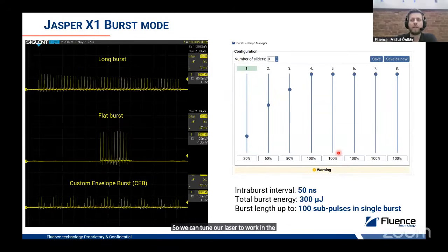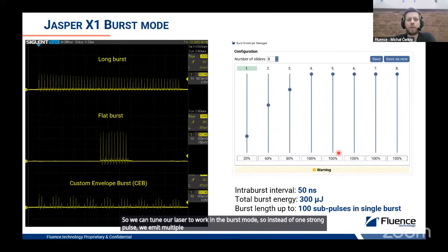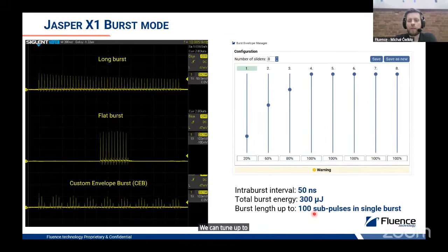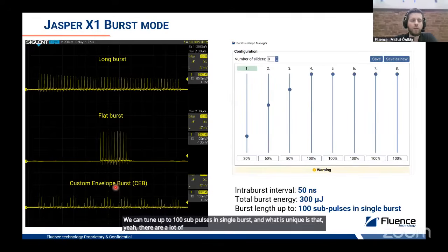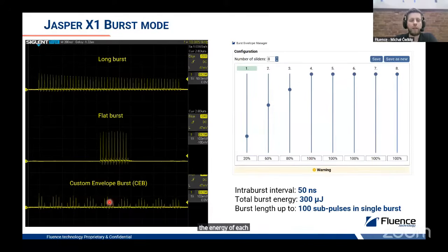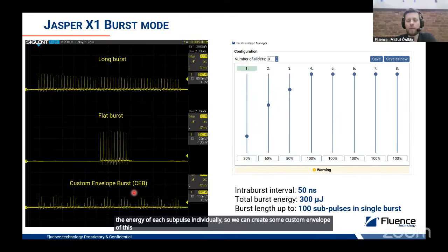So instead of one strong pulse, we emit multiple smaller sub-pulses. We can tune up to 100 sub-pulses in a single burst. And what is unique is that with a lot of sub-pulses, we can also tune the energy of each sub-pulse individually. So we can create a custom envelope of this sub-pulse package.